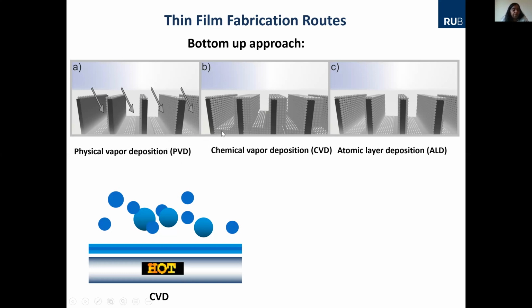Unlike in PVD, here some chemistry is involved. That means you have certain molecules called precursors. They are actually transported in the gas phase. These precursors are then reacted on the substrate surface. They can go through decomposition, and in that case, it's called chemical vapor deposition. So you see a hot substrate. The molecules here, these blue little dots, are the precursor molecules. Basically, it's a chemical compound. For example, it can be hafnium chloride for hafnium oxide. And then you can decompose them in the presence of oxygen, and you can grow hafnium oxide films. This is the method to grow hafnium oxide via CVD.